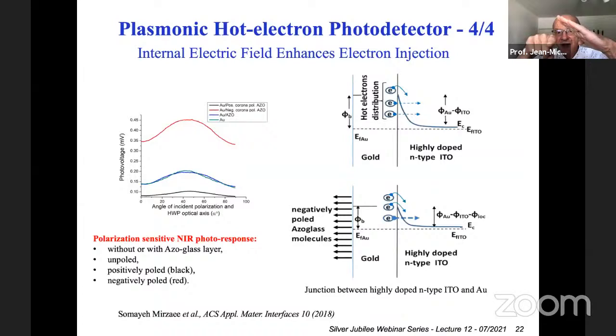And when it is in the S configuration, if you want TE configuration, we have a maximum of polarization that is parallel to the plane of the gold nanoparticles. So we have a maximum of absorption, and this is a situation. The third situation is S or TE, and the situation is P or TM. And this is how the photodetector works. I think that my time is over.